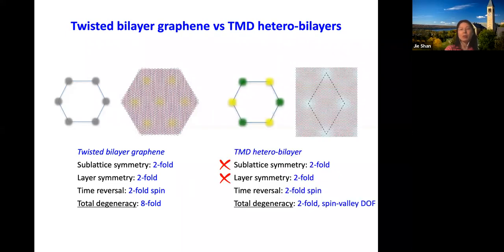That means you need to fill 8 electrons or 8 holes per Moire site to fill one band. The story is simpler in the TMD heterobilayer because the sublattice symmetry now is broken. So this is gone. The 2 layers are different, so this is also gone. What's left is only a 2-fold degeneracy, and that's the spin-valley degeneracy. So we need 2 electrons or 2 holes to fill one Moire band. Later I'm going to use a filling factor, which is the number of electrons per Moire site. So for example, filling factor equals 2 means 2 electrons per Moire site, and that's full filling for one Moire band.